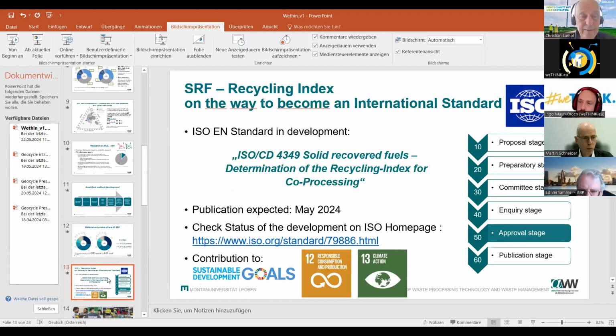These results end up then in the ISO standard. The ISO standard was mentioned by Hubert Grech already, because he has implemented it in the new Abfallverbrennungsverordnung in Austria. And what we want to achieve with the ISO standard is that this 16% or this 13% will be considered also as material recycling by the European regulation. Unfortunately, it was not done in the last change of the waste framework directive in Europe, but the target is that it will be done with the next framework directive change.